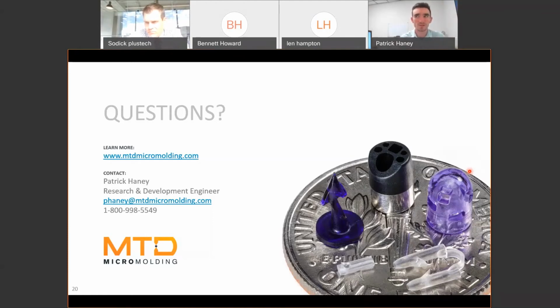So when we have polymers that are extremely crystalline, or an application that is dependent on that crystallinity, not saying that it's impossible, actually it's far from it, it's very possible, but sometimes we have to be creative to ensure that crystallinity does in fact complete. And then there are other polymers that you might be surprised about, like polycarbonate is a good example of a polymer that is very challenging to fill thin walls with, right? So we have many cards up our sleeve to coerce those materials to do what we want them to do and fill the areas that we want them to fill. But those are just a few examples of some of the challenges with some polymers that you would expect to be challenging, and then other ones that you wouldn't expect to be so challenging.